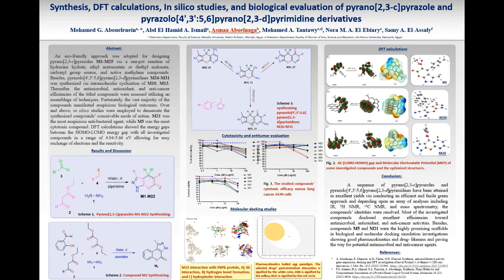Also, the chemical potentials, pi, of these compounds are in the range between -4.246 and -3.0346, which indicates that the electron cloud and the degree of absorption of both temperature and pressure are nearly the same. Furthermore, the chemical softness, the atom's aptitude for accepting electrons, was noticed in Table 12. M5, M8, M21, and M26 had values of 0.455943 electronvolts, 0.492647 electronvolts, 0.373445 electronvolts, and 0.452713 electronvolts, respectively. Many thanks to you.